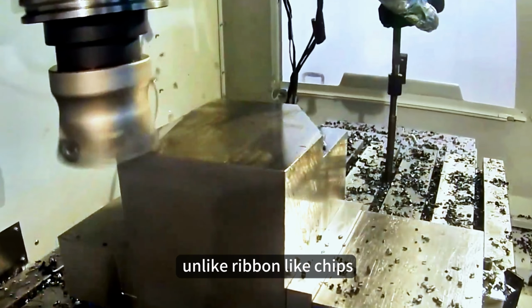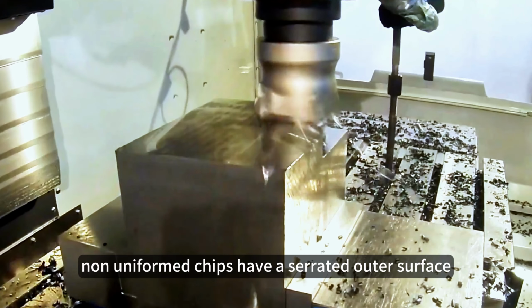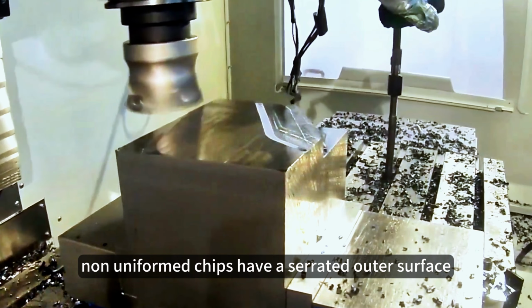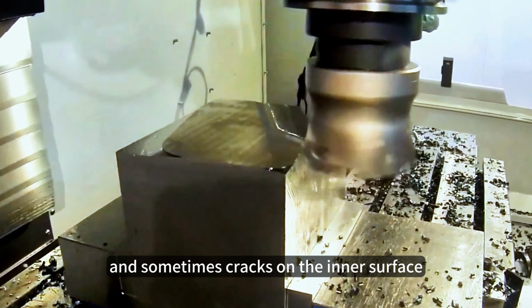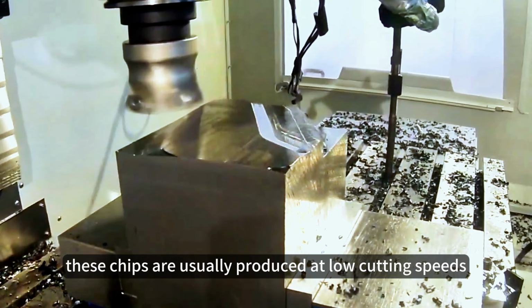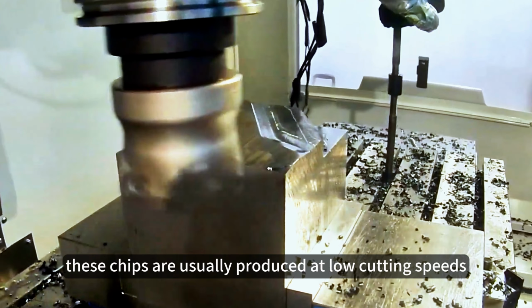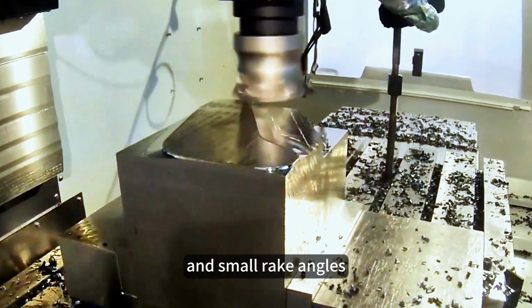Non-uniform chips. Unlike ribbon-like chips, non-uniform chips have a serrated outer surface and sometimes cracks on the inner surface. These chips are usually produced at low cutting speeds with large cutting thickness and small rake angles.